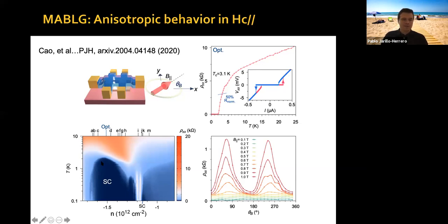If you measure the resistivity versus temperature, it looks a little different from before because it's a log scale, but this is the depletion in TC that I mentioned before. And if you measure the resistivity versus angle of the magnetic field, and then versus magnetic field, similar to the case of bismuth selenide, you can see these two maxima between 0 and 360 degrees. This means we have an ellipse. Let me actually show you the ellipse.